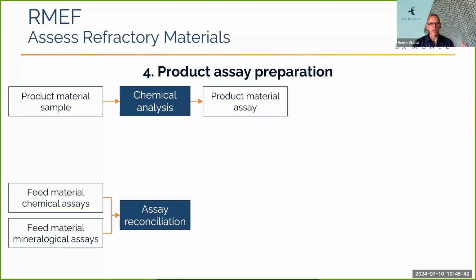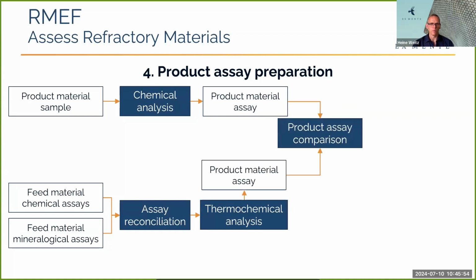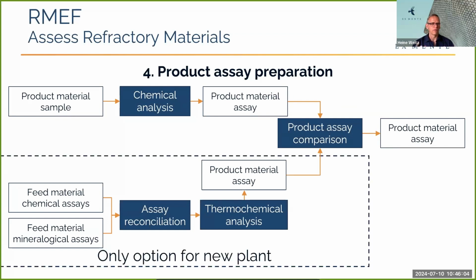Another approach is to take your feed materials, create a reconciled assay, and perform a thermochemical analysis to estimate what your product composition would be, and then to compare that with the actual products that you get from site samples. Now, this last approach is really the only one if you have a new plant. This is the only approach that you can follow to determine what your product material assay is, because you physically don't have product samples available.